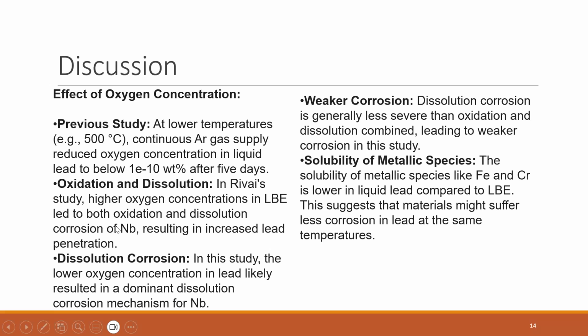And in the previous study, the higher oxygen concentration in LBE led to both oxidation and dissolution corrosion of niobium, resulting in increased lead penetration. And in this study, the lower oxygen concentration in lead likely resulted in a dominant dissolution corrosion mechanism for niobium. And for weaker corrosion, dissolution corrosion is generally less severe than oxidation and dissolution combined, leading to weaker corrosion in